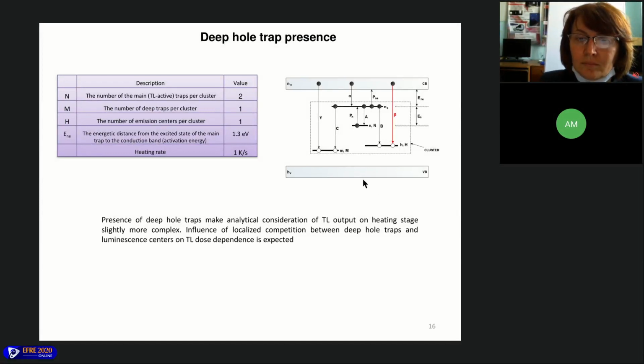Let us consider the case with deep hole traps in clusters. The presence of deep hole traps makes analytical consideration of TL output on the heating stage slightly more complex. Influence of localized competition between deep hole traps and luminescence center on TL dose dependence is expected.